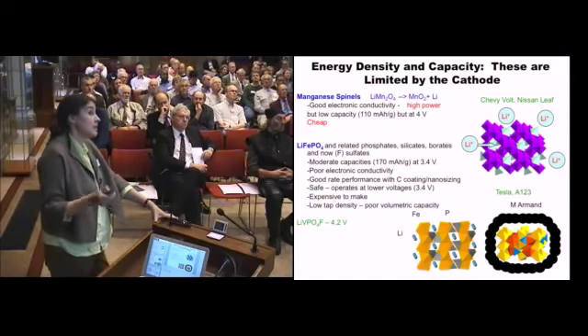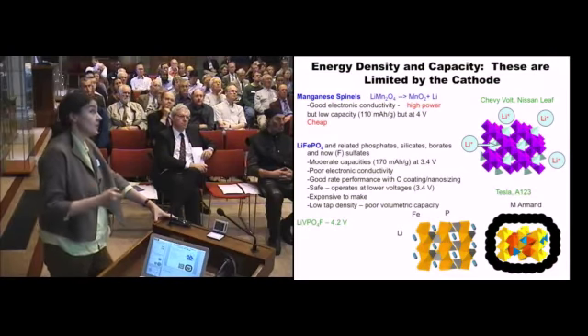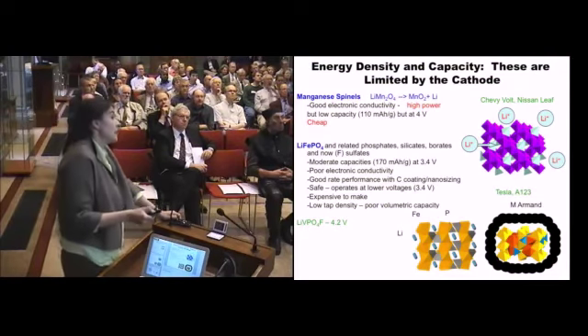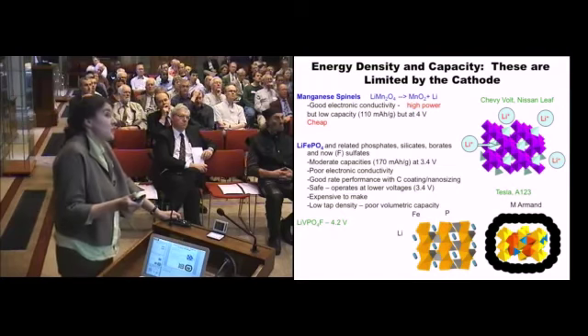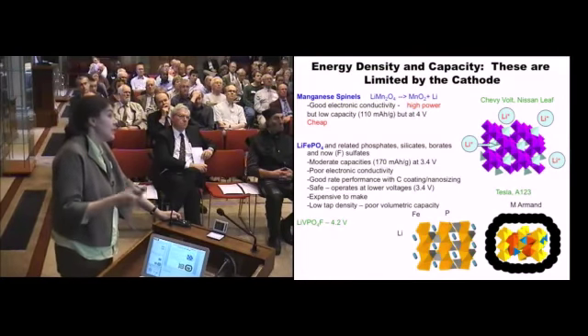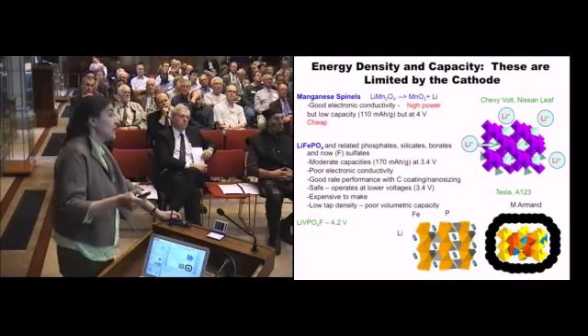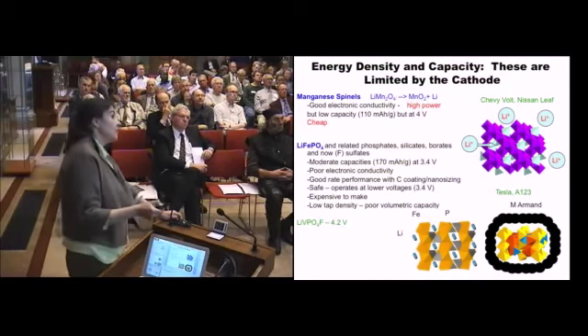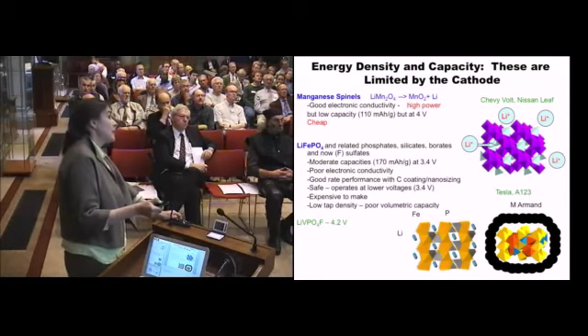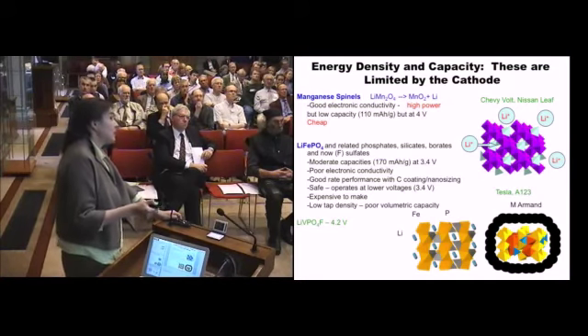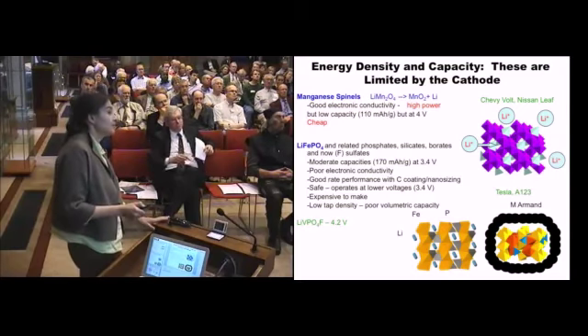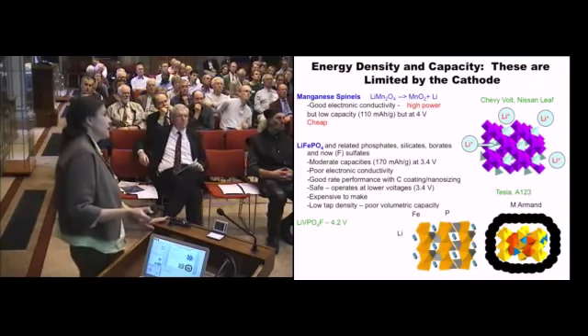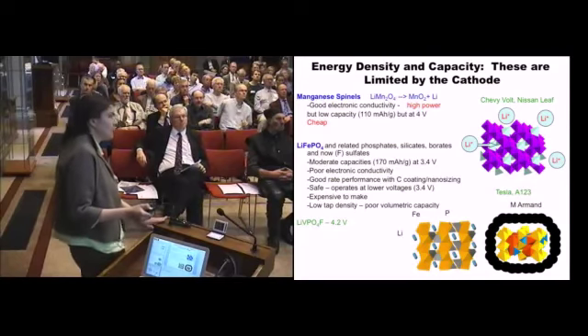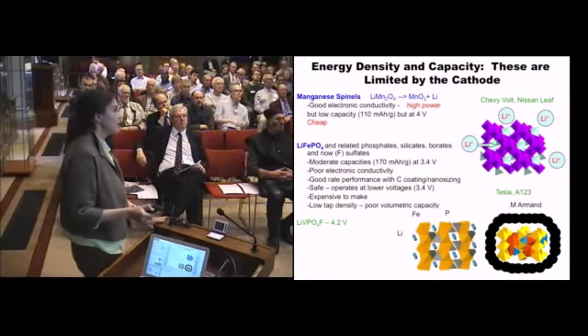And so this lithium manganese oxide technology is the first system that's going to go into the Chevy Volt and the Nissan Leaf. And it's cheap because it's got manganese in it. Your manganese ions are connected in 3D, and so you get very good electronic conductivity. So that with the lithium transport and electronic transport gives you high power. The disadvantage is you've got one lithium for two manganese, so you've got inherently low capacity. So it's about the same as lithium cobalt oxide. Then there was a really interesting advance. So John Goodenough, the same person who did lithium cobalt oxide, had been looking at lithium iron phosphate.